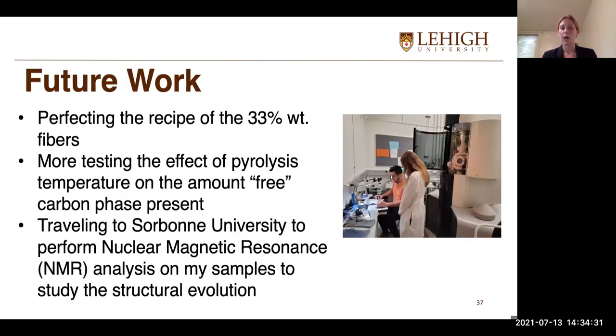So in the future, I'm going to be working on perfecting the recipe for the 33% weight fibers. I did struggle with finding the right amount of water to add because I noticed that the amount of water I added definitely affected the quality of the fibers. So I'll be working a little bit more on that in the future. Also, I will be doing more testing on the effect of pyrolysis temperature on the amount of free carbon phase present. You probably noticed that I pyrolyzed the powders at 3 temperatures, but I have not yet pyrolyzed my fibers at 1000. So I'm planning to do that in the future.